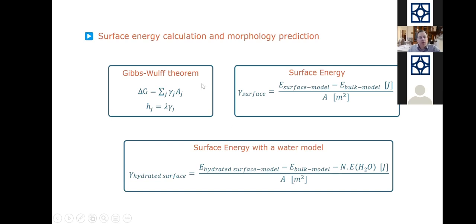Now, in order to obtain these morphologies, there is a thermodynamic law that helps us to draw these model morphologies. And this is the theorem of Gibbs-Wulff that will help us with that. And it has the following form. So we have a delta G, so the free energy of Gibbs, which is equal to the sum over the free energies of one orientation multiplied by its surface. This means that in fact, for a constant free energy value, we have an opposite relationship between the surface area and the surface energy. Yeah. Low surface energy will expose large areas.